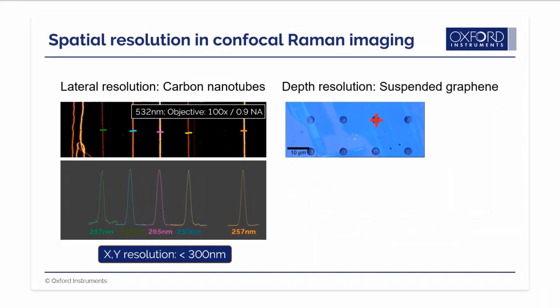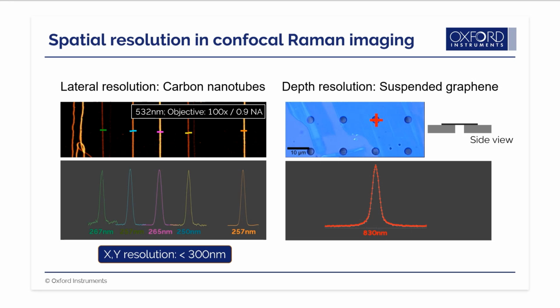Secondly, the depth resolution. This is typically a bit lower because this is the direction of the laser light. To test the axial resolution, we use a graphene layer suspended over holes in a silicon substrate. This is a schematic side view of the sample. Graphene is a monolayer of carbon atoms, making it perfectly suited to measure the depth resolution. The Raman spectrum is similar to that of nanotubes, so we can investigate the same G-band. Now we acquire Raman spectra while moving axially through the graphene layer and again calculate full width half maximum of the Raman signal. We observe an axial resolution of less than 830 nanometer.